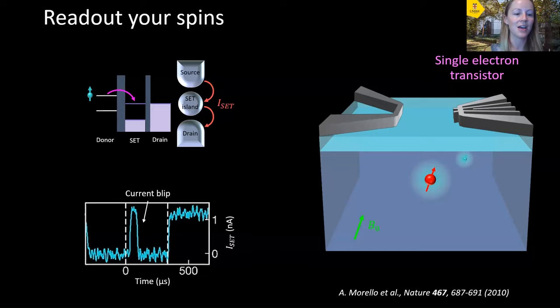And because this single electron transistor is a very sensitive detector for the local charge environment, it will have a current flowing through the SET when the donor is ionized. And then when the electron tunnels back onto it, the current goes away again. So we observe something called a current blip when we have our electron being a spin up and causing the donor to become ionized.